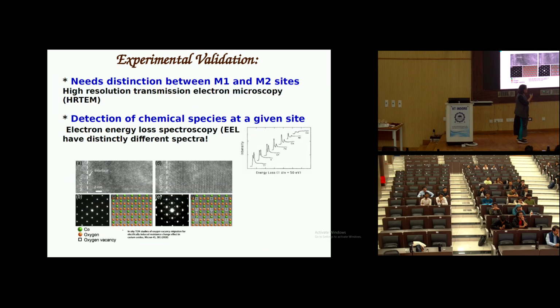Now, how can an experimentalist actually detect this? Apparently such a thing for the oxygen vacancy was done for cerium oxide. No one has done it in this mineral. So all you need is to make a distinction between the M1 and M2 site. If you have high resolution transmission electron microscopy, you can basically resolve between the M1 and M2 site. And then I need to resolve whether it's iron or magnesium, and for that you can use electron energy loss spectroscopy. So no one has done this experiment, but this is what our prediction is. If you can manage to do this experiment, you will be able to follow the path the vacancy has moved.